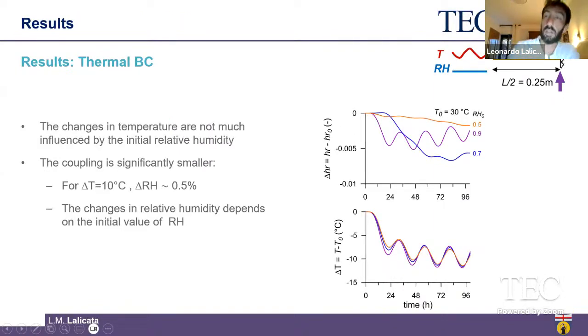And if we have a look at the other problem, the thermal boundary condition, we observe two things. First of all, the coupling is significantly smaller, which means that you see the temperature reduces by about 10 degrees at some point, and this change in temperature of 10 degrees corresponds to a very little change in relative humidity of about 0.5%, which from an engineering perspective is practically zero. And what is important also to note is that this direct problem here is not really influenced by the initial values of relative humidity, but the coupling, even if little, yet it is influenced by the amount of water, the amount of relative humidity we have in our samples.